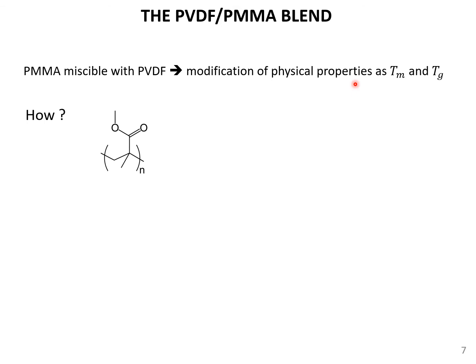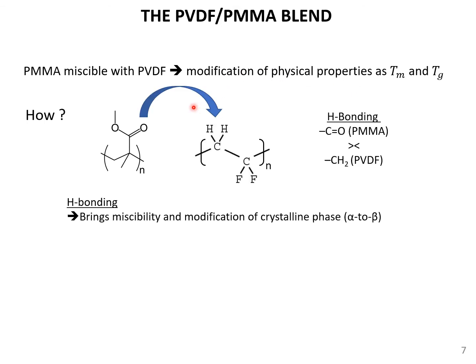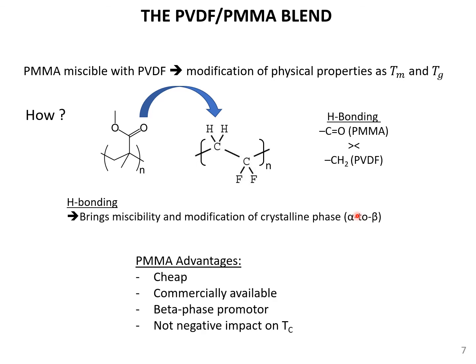The reason that PMMA is very interesting is simple: when you look at the macromolecular backbone of PMMA versus PVDF, you can see the possibility of hydrogen bonding between these two moieties, and therefore you can bring some miscibility and modify the crystalline phase, passing from the alpha to the beta phase. Of course, PMMA is well known as a plexiglass material, it's cheap, commercially available, and can promote the beta phase without having any impact on the Curie temperature, in contrast to copolymerization.